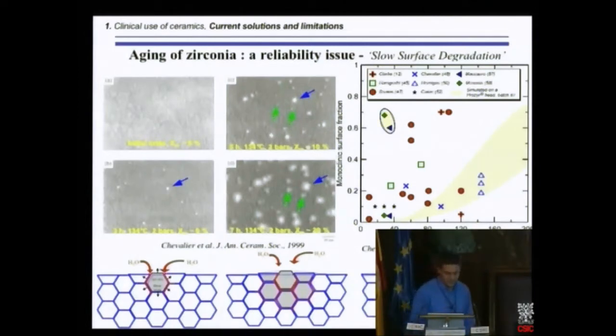And let's put this zirconia inside a steam sterilization autoclave. After 3 hours in autoclave, at 134 degrees C and 2 bars, there is still no measurable monoclinic content at the surface, but you can see with optical microscopy images, these are Nomarski contrast images, the relief. You can see some white spots, meaning that you have some surface uplift at the surface, after only steam sterilization for 3 hours in autoclave.